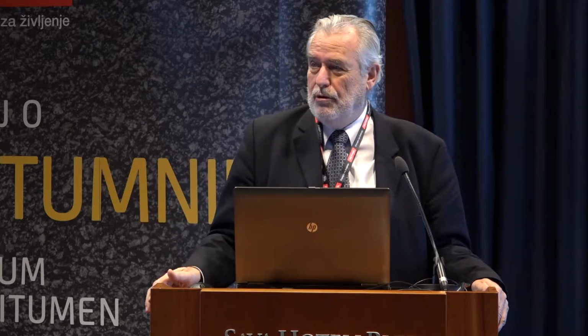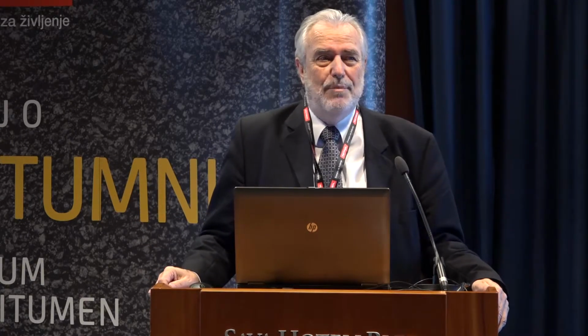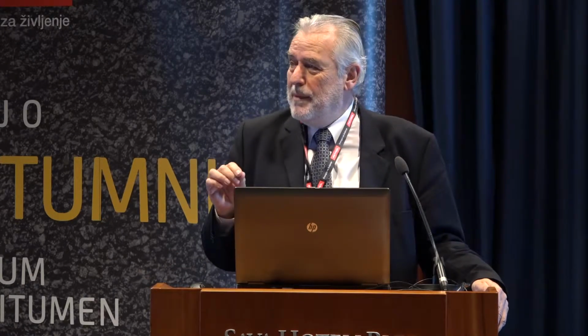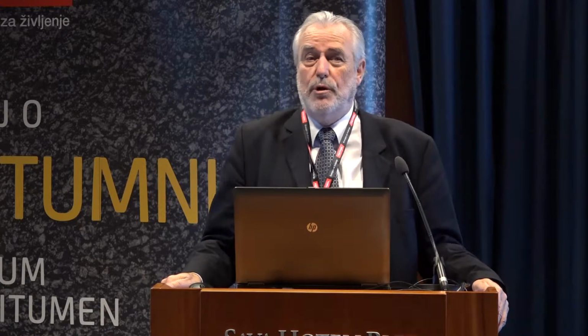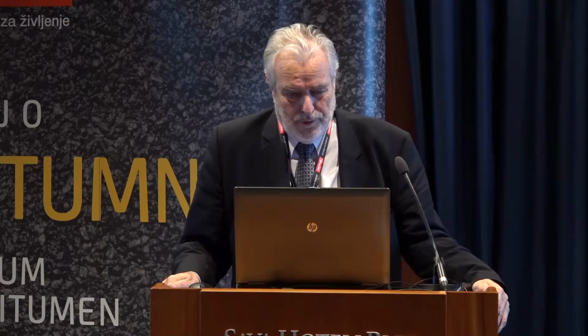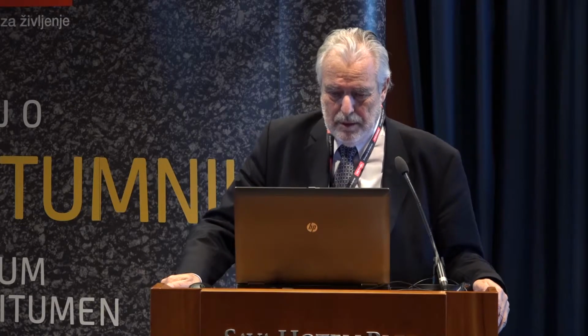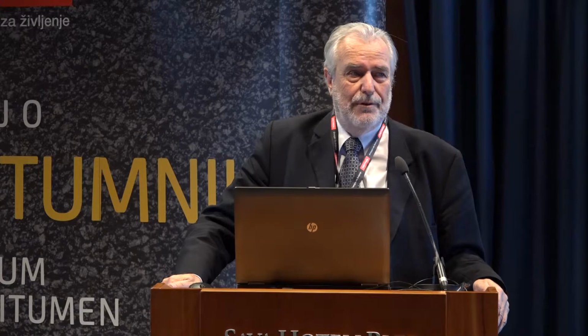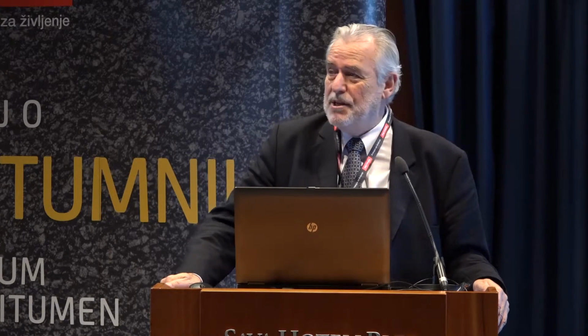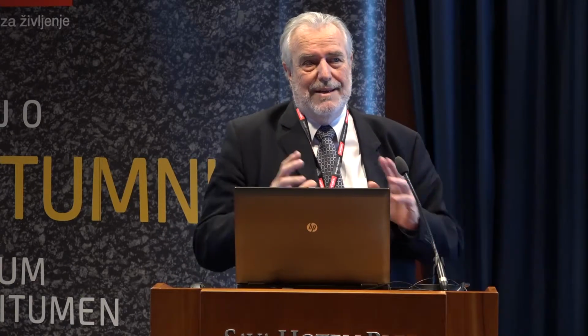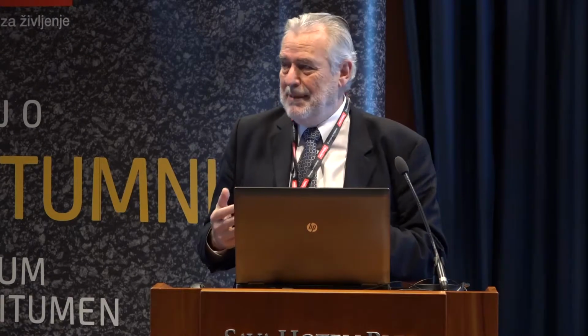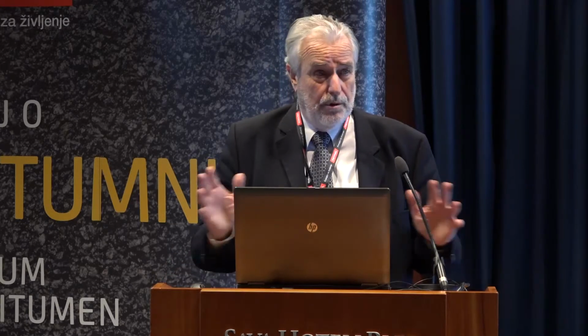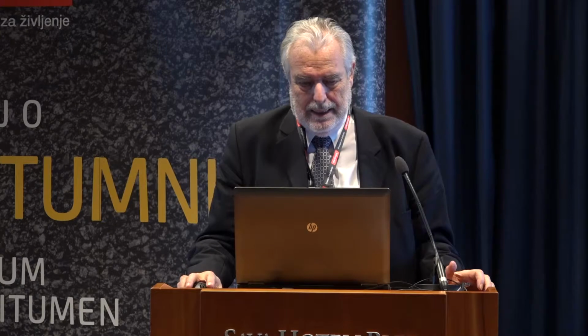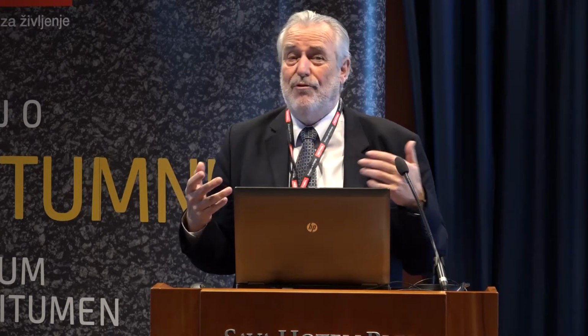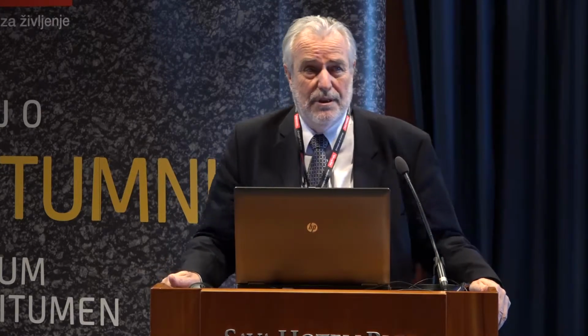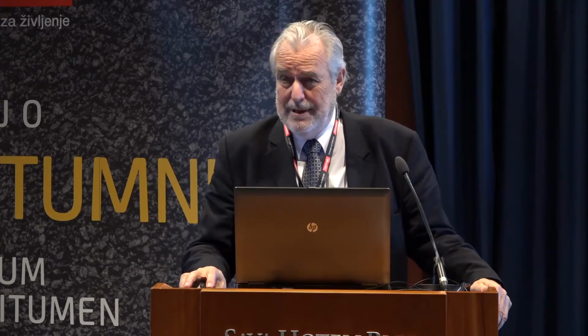Now, Mrs. Turk has shown what the improvements can be when you look at the laboratory. But there are not too many studies that have demonstrated whether PMBs really work in practice. In that respect, I need to refer to a report that was issued by the Asphalt Institute in 2005. They made a tremendous effort in comparing PMA sections next to unmodified sections under the same climatic conditions and under the same traffic loading. So they were literally next to each other. One thing that you have to remember is that the average level of modification in the United States for polymer modified asphalt is about 2.5% to 3% of polymer in the binder. So that's not a lot.